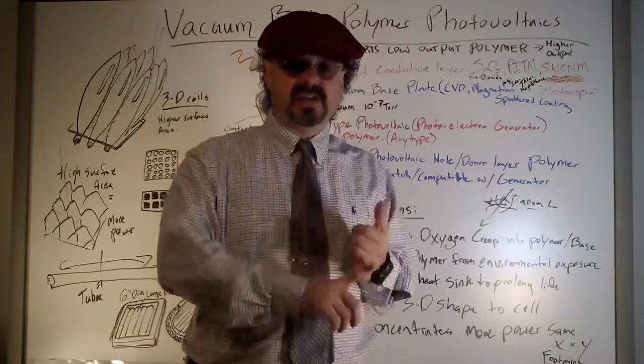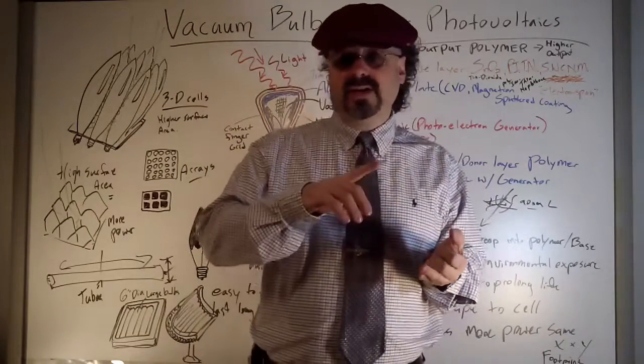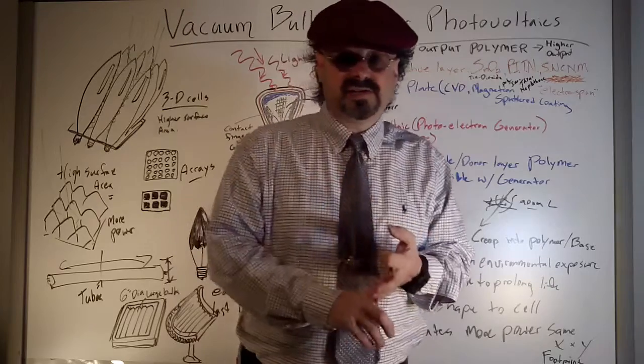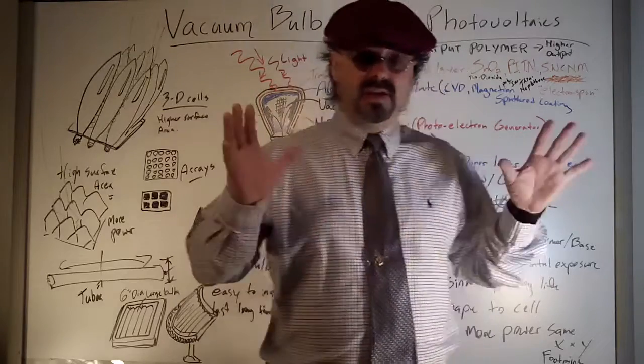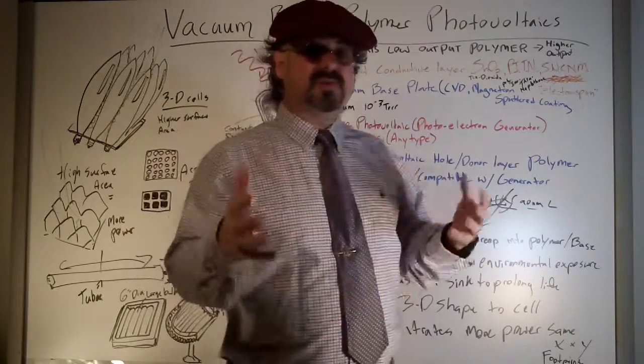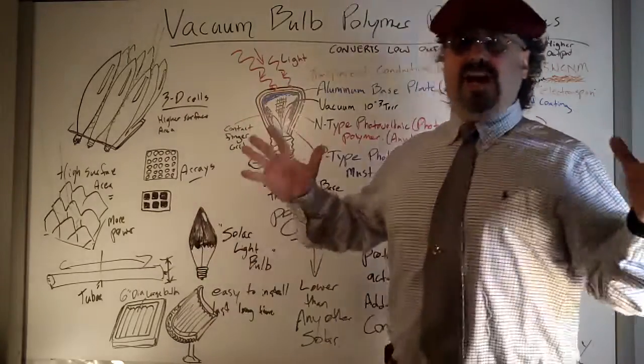And they fail because of oxidation. They fail due to heat creep. They fail due to oxygen creep. But the main thing is the oxygen creep. So all of those things combined, what's the biggest point of failure? And that's the oxygen creep.